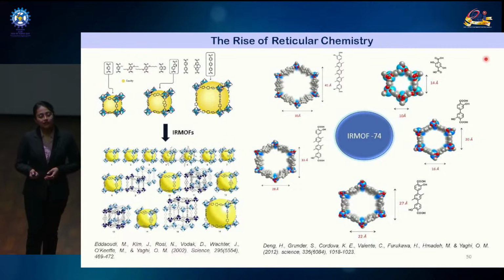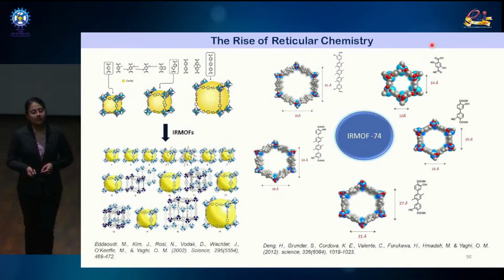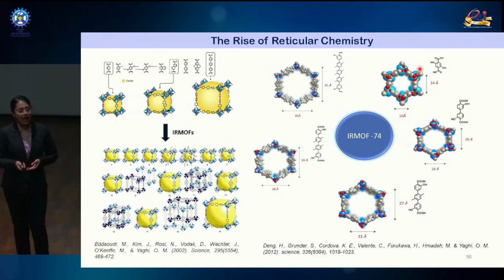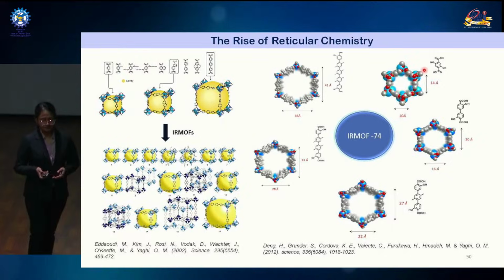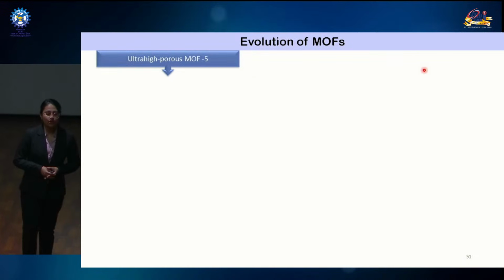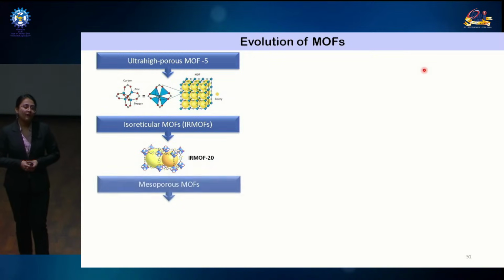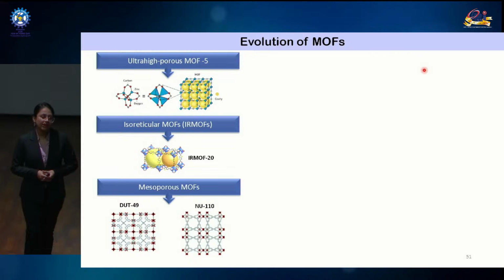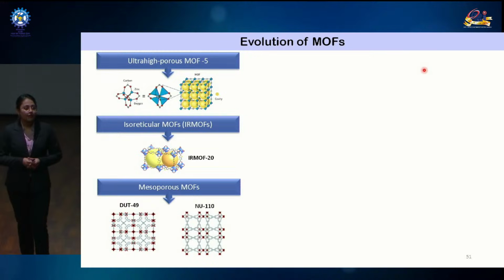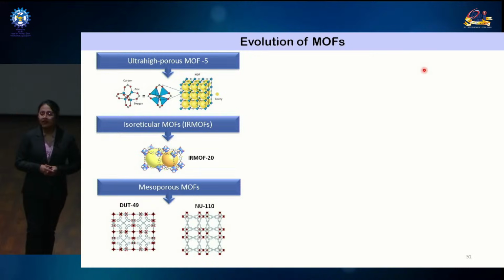Here also, while he tuned the organic linkers without changing the underlying topology, he saw that changing the organic linker eventually led to changes in the pore aperture. As he increased the length of the organic linker, it eventually led to an increased pore size, pore volume, and eventually an increased surface area. So, a simple understanding of how MOF-5 was designed and eventually constructing the IRMOF series led to the MOF's evolution from a simple microporous material into a mesoporous framework that had larger cavities.